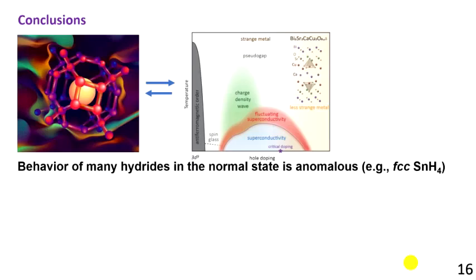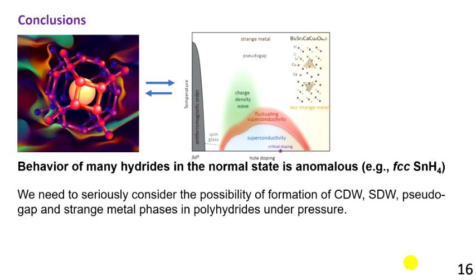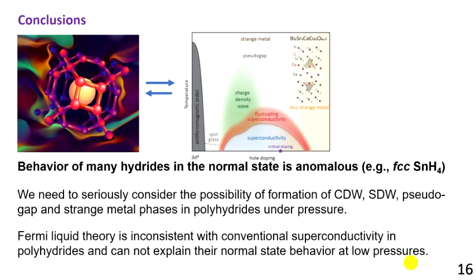In conclusion, I would like to underline that behavior of many hydrides in a normal state is anomalous. We need to seriously consider the possibility of formation of charge density waves, spin density waves, pseudo-gap, and strange metal phases in polyhydrides under pressure. And Fermi-liquid theory is inconsistent with conventional superconductivity in polyhydrides and cannot explain their normal state behavior at low pressures.